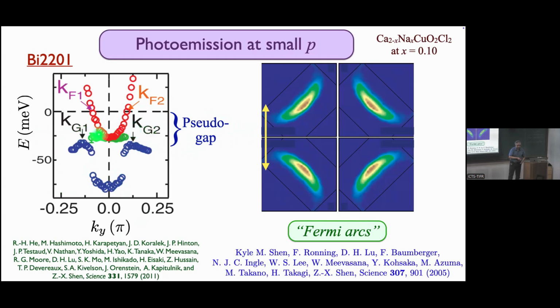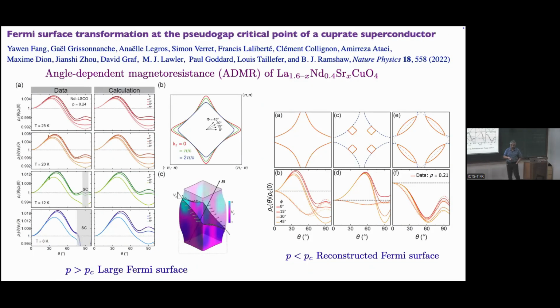And this green line is something that develops below TC. That's believed to be the pairing gap. So there's a clear difference between what's called the pseudogap, which is present all the way up to T star, and then the pairing gap, which only develops below TC. All right, so that's the basic characteristics from photoemission.